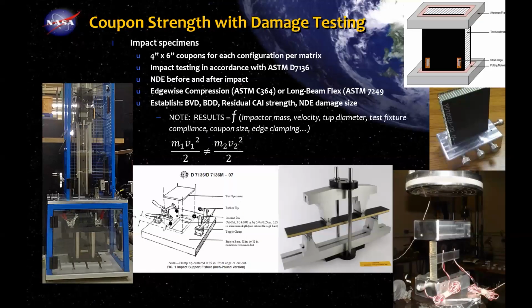Okay, so when we get into testing, and I'm telling you, we got to test for damage tolerance. Now I'll disclose that our test methods, they really kind of suck. And this ASTM standard way to do this from a compression after impact standpoint is to utilize this ASTM 7136. On the left is a picture of a drop tower.